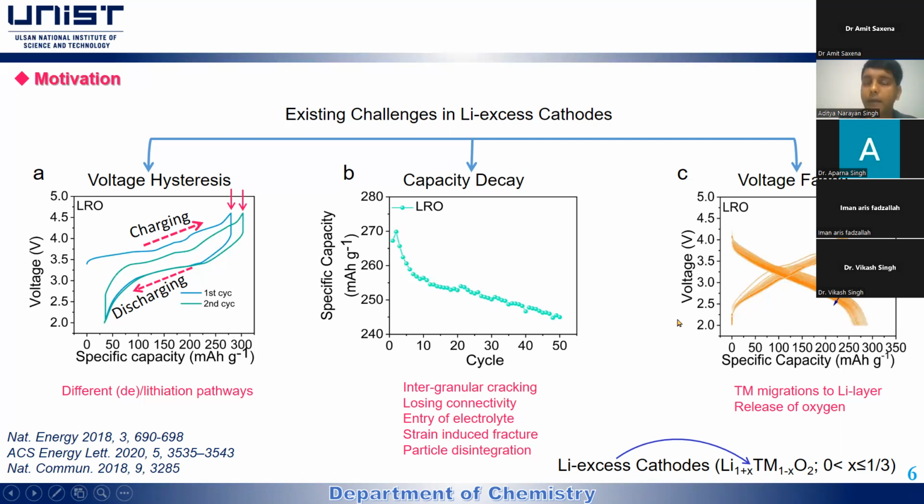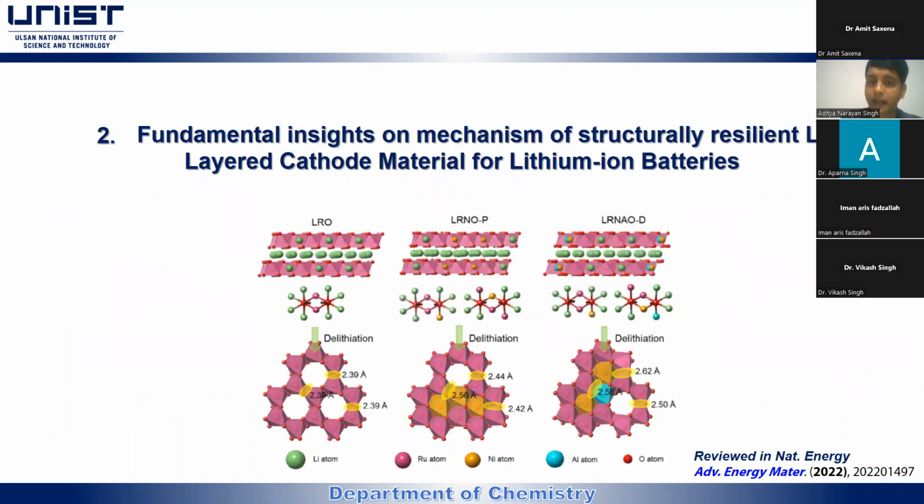Quite often, we also see that our phone batteries do not get close to 100%. That is what is known as voltage fade in batteries. Voltage fade usually happens because the transition metal and lithium ions get swapped, so the lithium does not get its original position occupancy. That causes the voltage fading issue. So what I mean to say is, these are the major issues whatever battery you choose, whether lithium-ion batteries, lithium oxide batteries, or any batteries. Researchers can take this as a stepping stone for their research activities. How could we make a battery structure resilient to these damages? This was my driving factor.